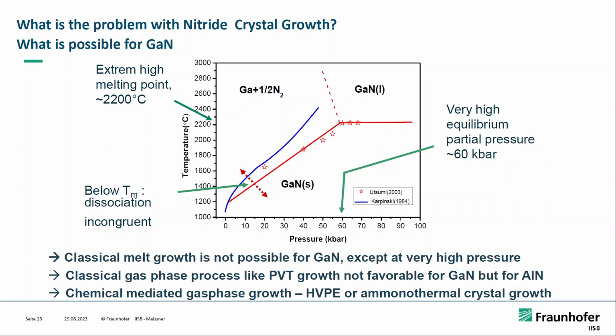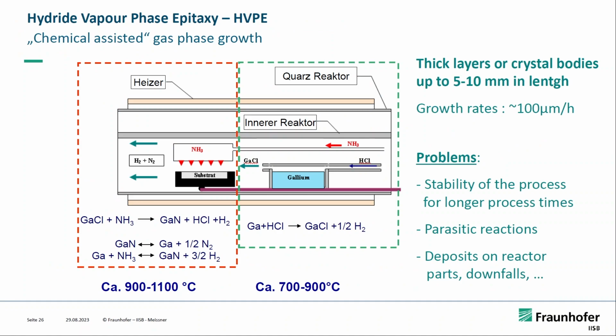So you have the classical gas phase process, like PVT, which is not favorable, and could be done for aluminum nitride, but not for gallium nitride. So we choose a chemical mediated gas phase growth, to keep the gallium nitride in gas phase by adding chloride. This is the HVPE process, which you can see here for a horizontal reactor. There are other reactor types existing, but this is the bare principle.